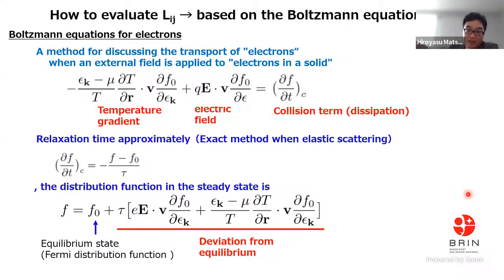To get Lij theoretically, we use the Boltzmann equation. This is the Boltzmann equation. On the left-hand side, we have two terms: one coming from the temperature gradient and one coming from the electric field. The right-hand side comes from the collision terms, which are the origin of the dissipation. And using, for example, the relaxation time approximation, we can get this one.